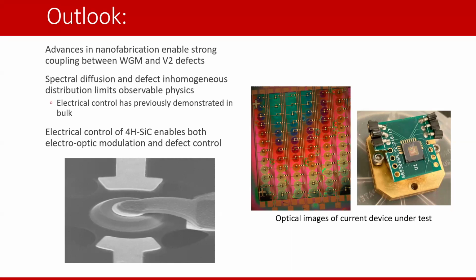One more? Yeah, of course. Between the electrodes, how does the electric field pass? What is the tolerance between the electric field lines and the optical mode? Yeah, this is what I ran into with my quality factor. Before, when we were pushed out at 8 micron separation between this and this, the quality factor was unchanged, which means there's no interaction between the electrodes and the optical mode. But as soon as I brought them in another 2 microns closer, we see a drop in the quality factor by a factor of 8.